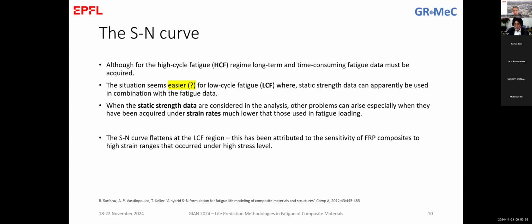To show this difference between the behavior of the material in static or fatigue loading, we can see that for a lot of materials, the actual behavior shows that the S-N curve flattens at the low cycle fatigue region. This means that the S-N curve of composite materials does not have a continuous trend of a power curve, does not have the same slope in all three regions, but it is actually segmented. And at the low cycle fatigue, it has a lower slope that becomes higher and probably continuous until the high cycle fatigue after a kind of transition region in between. We discussed this change in a publication that we did in 2012 with one of my previous PhD students.